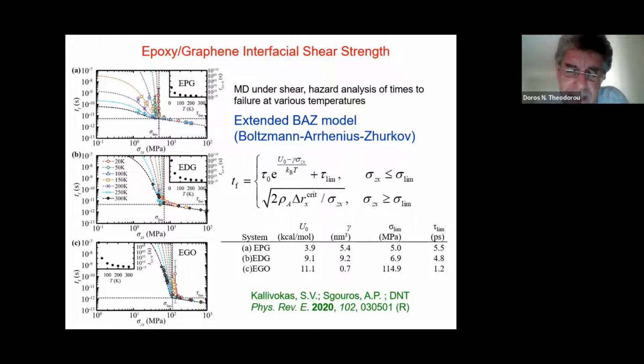Also, one sees that the activation volume, this gamma, which is a measure of how delocalized essentially this process of failure of the interface is, depends quite a bit on the type of the interface. It is quite large for the pristine graphene and even larger for the defective graphene, suggesting a delocalized failure process. However, for the graphene oxide, it is quite small. And this, we think, is related to the fact that the failure really initiates at an individual OH polymer association. These OH groups associate with polar groups in the polymer.